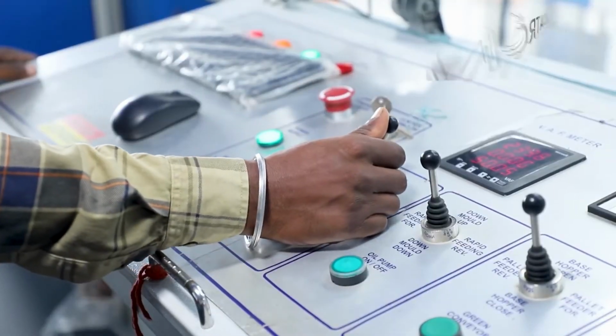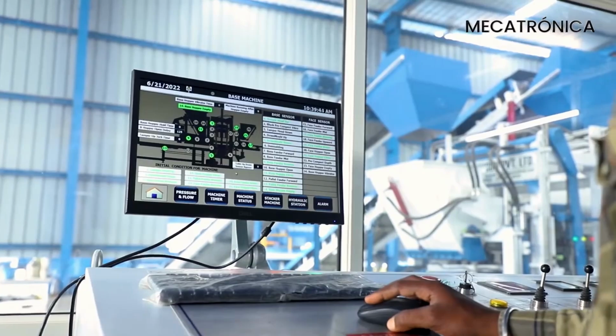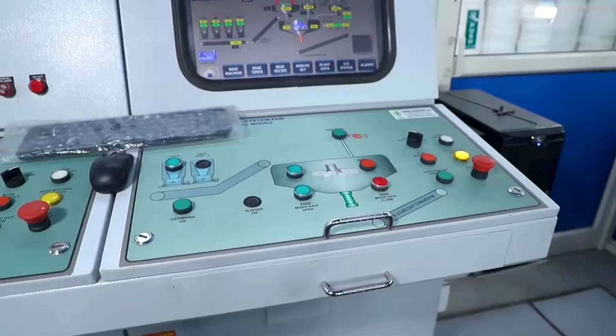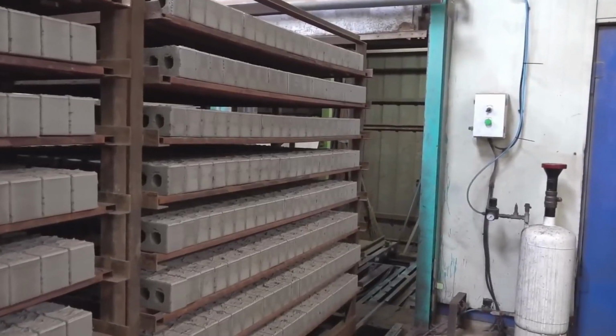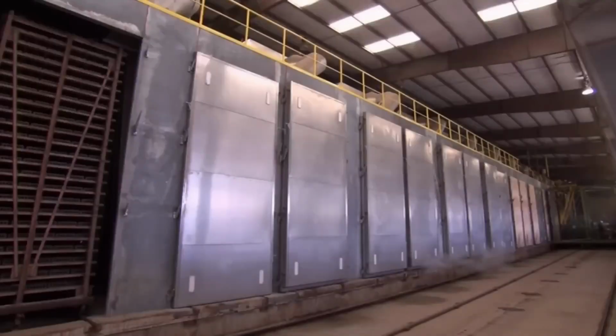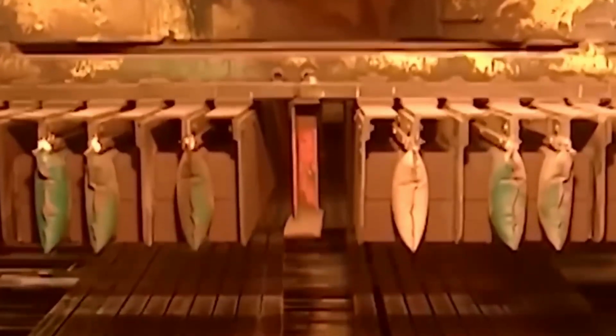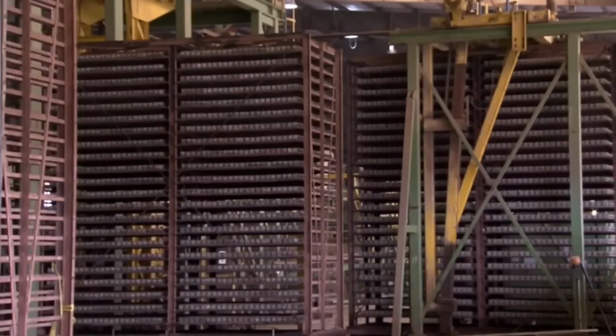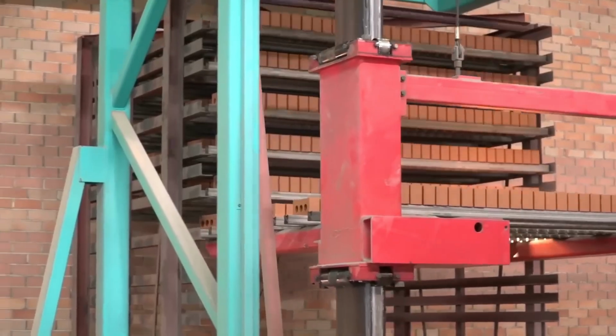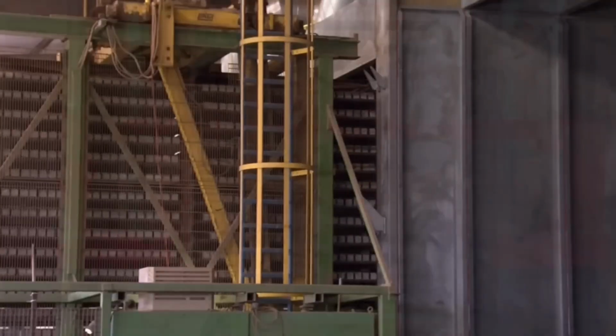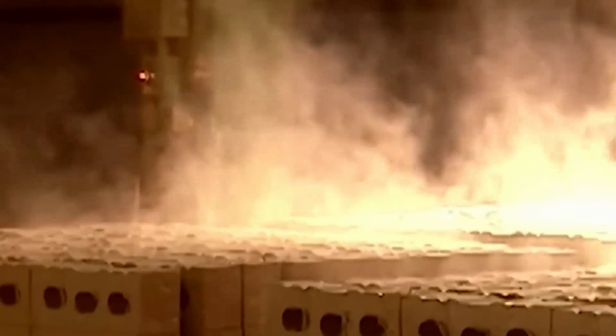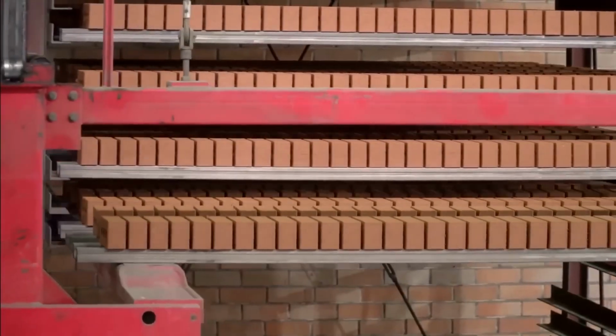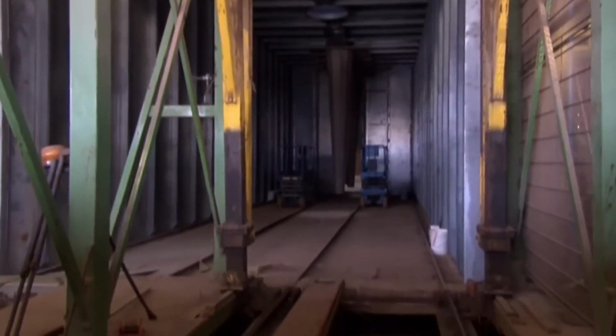Although the bricks have already passed through the drying area, they can still retain residual moisture in internal pores. If this moisture turns to steam too quickly, the pressure can fracture the piece. As the wagons advance, the temperature rises. Significant chemical changes occur at this stage. Organic matter burns, some minerals lose structural water, and carbonates decompose, releasing carbon dioxide. The clay changes its internal structure. This process must be precisely controlled because each reaction occurs within a specific temperature range. Too rapid a rise can cause defects. Too slow a rise consumes more energy and reduces productivity.